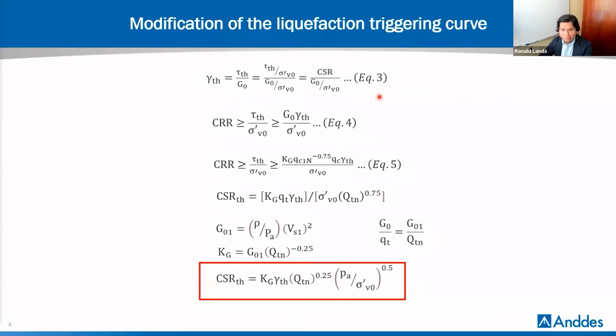The minimum value of liquefaction cyclic resistance represented by the threshold cyclic shear strain can be related to the CRR as presented in equation 4 and equation 5. So if you derive each line, then you end up with this form of the liquefaction triggering curve, but equated. It's no longer empirical, it's now equated.